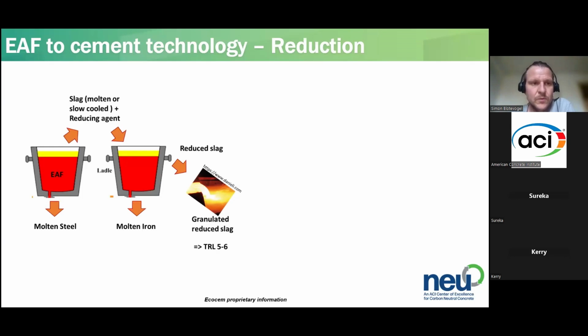So that was it for granulation for the moment. So, and I would like to move to reduction. So reduction would start the same as the granulation. You would pour your steel, and then you would move your molten slag into another ladle where you would remelt it. And then add some reducing agent, which can be different things, really. It can be carbon, can be hydrogen, can be maybe even electrolysis. And then the reduced slag will be very similar to granulated blast furnace slag, would be quenched.